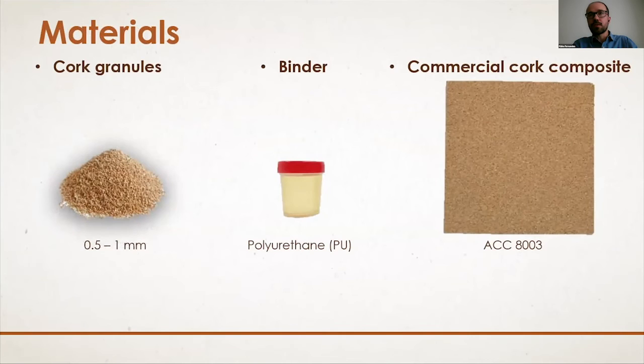So in order to assess the resistance to UV, a commercial cork composite was used. This one is manufactured by compression molding, using cork granules between 0.5 and 1 millimeter, and thermosetting polyurethane binder. This results in isotropic specimens with an average density of 200 kilograms per cubic meter. And due to the limited dimensions of the accelerated weathering chamber, we had to stick with 8 millimeter thick sheets for exposition to UV. So we have a limited thickness.